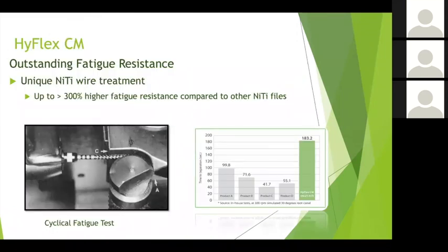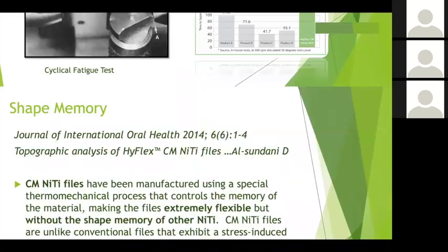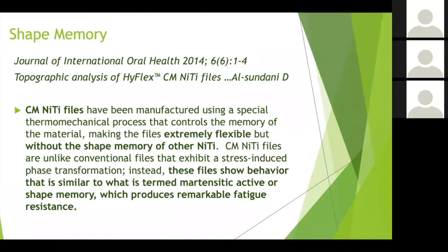And so she puts them in, this is what the device looks like. You put your file in, you can create the kind of bend by adjusting B, and that changes your bend. But her results found she was way above for cyclic fatigue over the conventional files. And so that starts that process where we start talking about, oh, we've discovered that controlled memory now has a greater cyclic fatigue. So what does that mean? Cyclic fatigue is how many times you can spin a file before it separates on you.